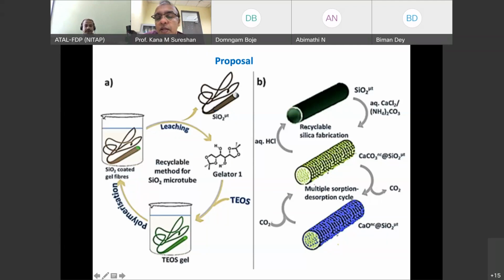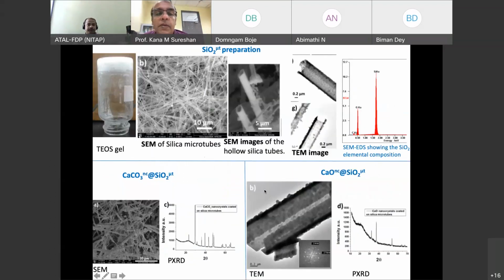This hollow cylinder is of micrometer size. So that means we can grow nanocrystals on the silica surface. By simply taking calcium chloride and ammonium carbonate solution, we can grow crystals of calcium carbonate on the silica tubes, both inside and outside. And upon heating, this will give nanocrystals of calcium oxide. Now it will have more surface area. It's expected that it will have more efficiency in terms of carbon dioxide absorption.